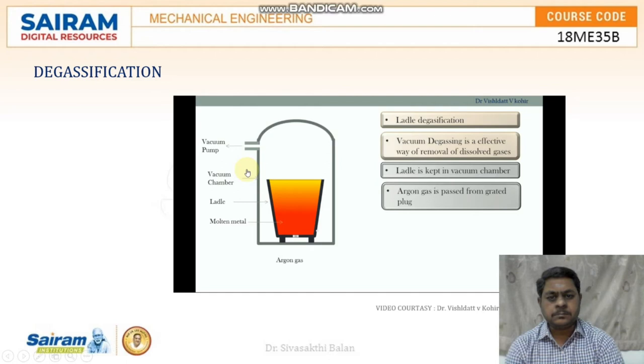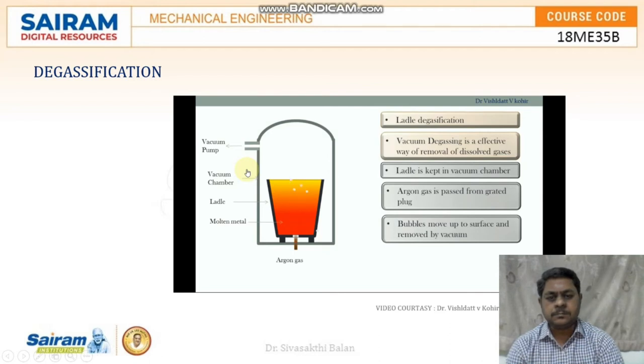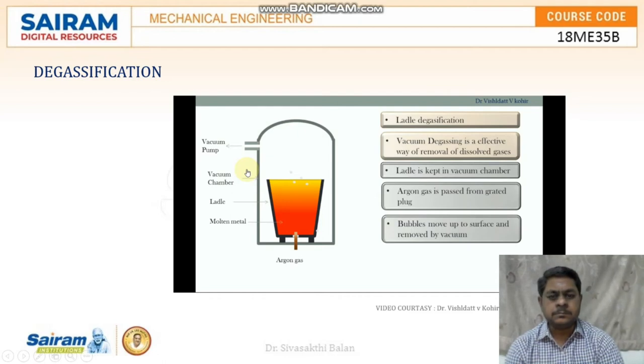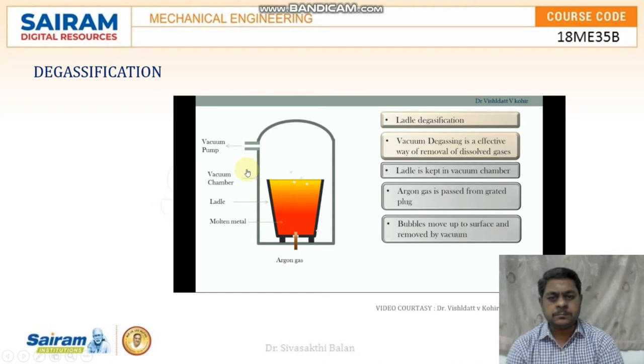We use argon gas, which is passed through the ladle, normally from the bottom. When the argon gas passes through the molten metal, it carries away hydrogen with it. We want small bubbles, which will have a longer retention time in the ladle, so that the maximum portion of the dissolved gas elements can be removed. The bubbles moving upward to the surface of the molten metal are removed by the vacuum present in the chamber.